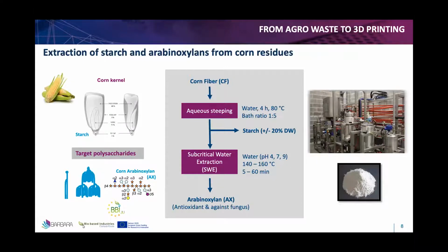That previous work was related to the functional molecules, and now the extraction of starch and arabinoxylans from corn residues was also carried out. In this case, subcritical water extraction was used as a green technology compared to conventional organic solvent extraction methods, because it used non-toxic green solvents, and in this case, just water was used. So with these technologies applied to large volumes of vegetable matrices in continuous extraction processes, we could obtain the different polysaccharides that were used as part of the biopolymeric matrix in the project. And you can see there the biorefinery station of the Celabor partner, in this case, for the upscaling purposes.